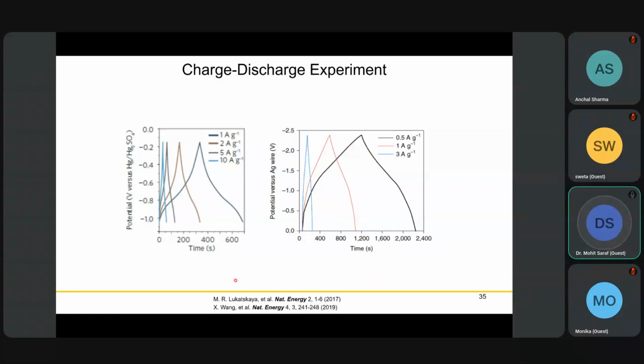Again, when you get charging and discharging curves at different current densities, the first thing to check is whether they are symmetrical or not. If you draw a straight line and the area on this side and that side is equal, then you can estimate your system is coulombically efficient and go ahead with calculating your capacitance. But if they are not equal, you should redo your experiments, or check what is happening with your cell and system, and whether your channel is stable.